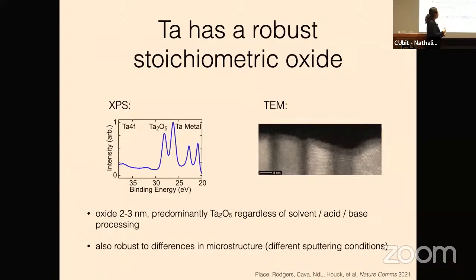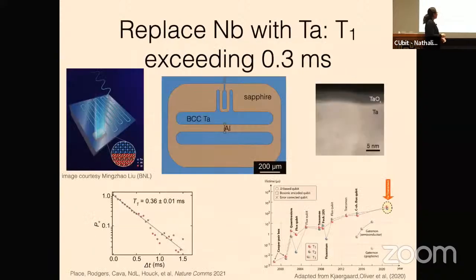And this oxide looks very robust to differences in microstructure and sputtering conditions, so really no matter what you do, you always get the same oxide. And the headline result is that by doing kind of this simple swap and being careful about our fabrication and cleaning off the substrate, we were able to routinely get lifetimes exceeding 300 microseconds, so about a factor of 3 over the previous state of the art. And this is a very robust result. So we see this on essentially every single device that we make.